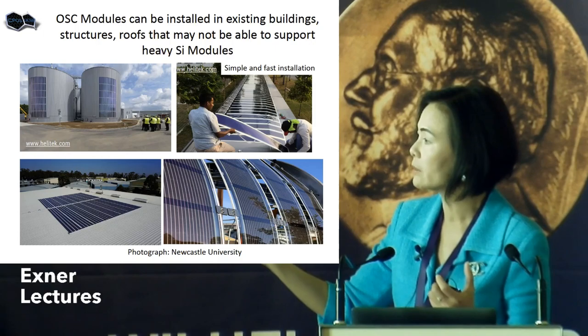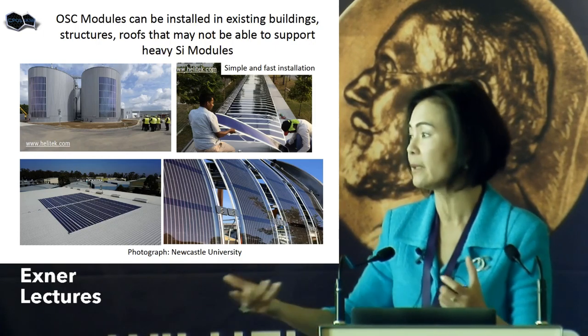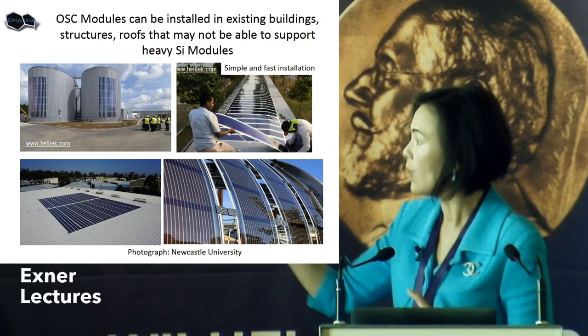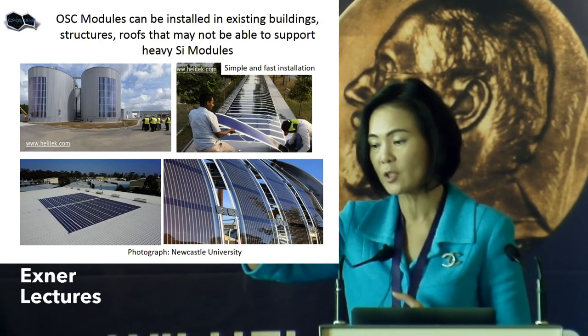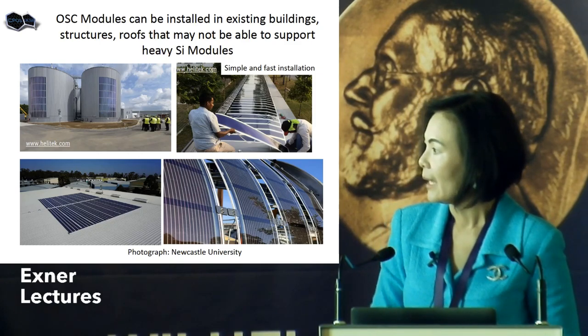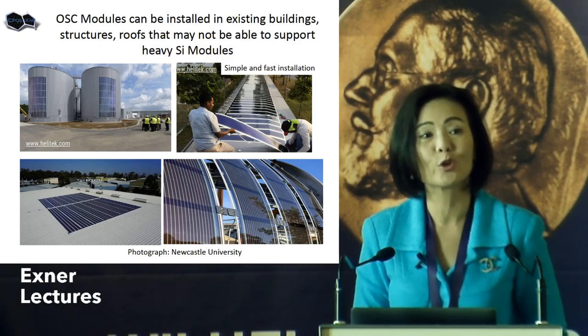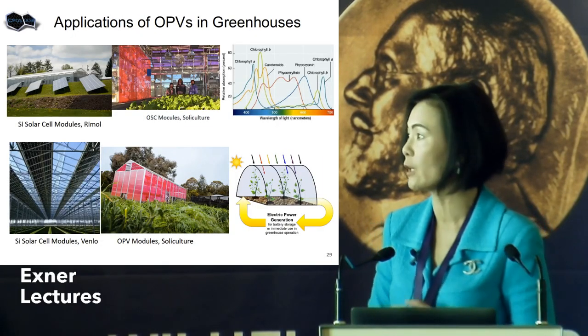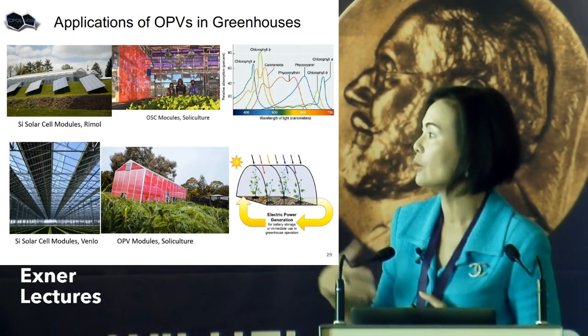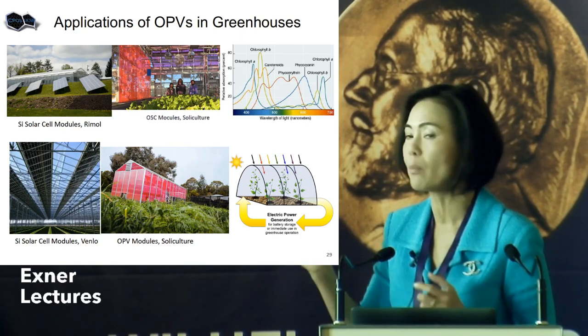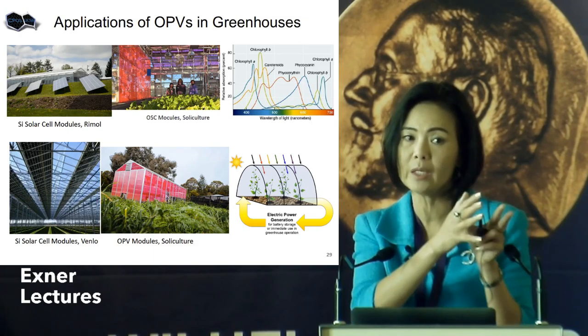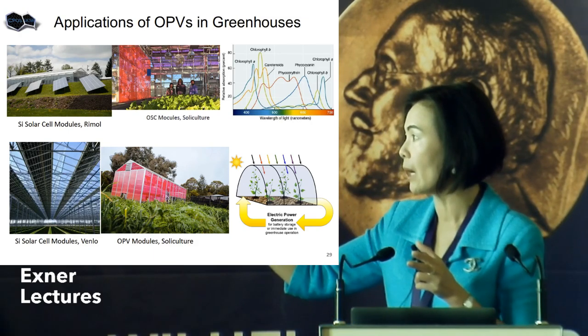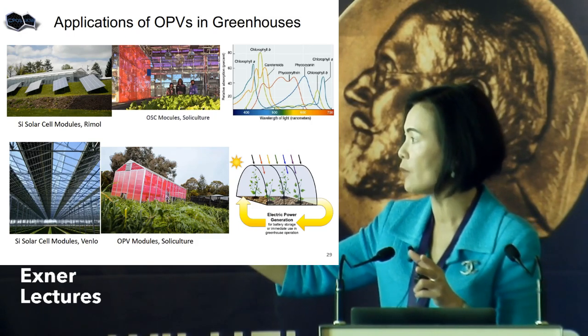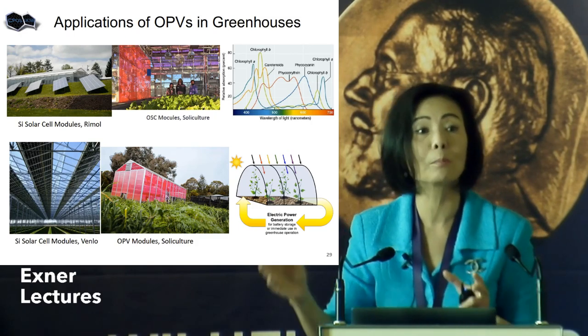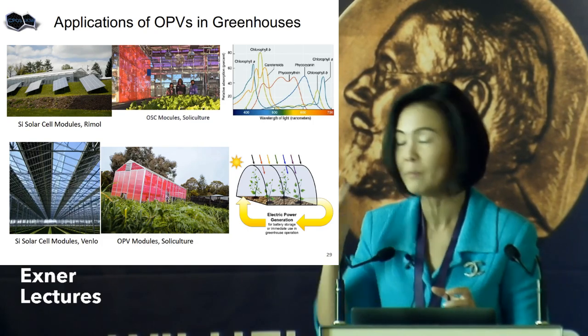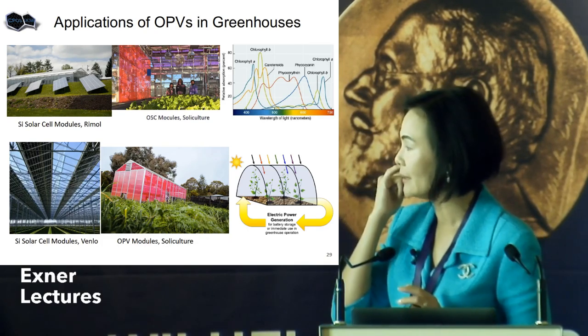For example, for certain building structures that cannot take the heavy weight of silicon solar cells, now you can actually put on the flexible OPV module. And so we can also use it to power the greenhouse. For example, you can control the band gap of the material. For greenhouse application, it's very important that the material absorbs in the UV or the near infrared, because you need to leave open the photon energy between 400 to 700 nanometer for the plant to absorb to do photosynthesis. Okay? So if you block that, basically the plant dies.